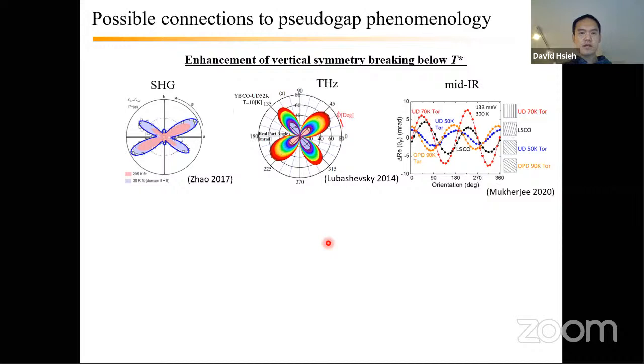One of which is, this vertical symmetry breaking that we observe in SCOC is not new in the sense that our old YBCO data also showed this loss of vertical mirror symmetry, at least compared to the published structure that was refined from diffraction. And in terahertz polarimetry, they had also shown that this vertical mirror symmetry breaking gets enhanced below T star. And that has been extended more recently all the way up to the mid-infrared and even the visible range of optical detection.